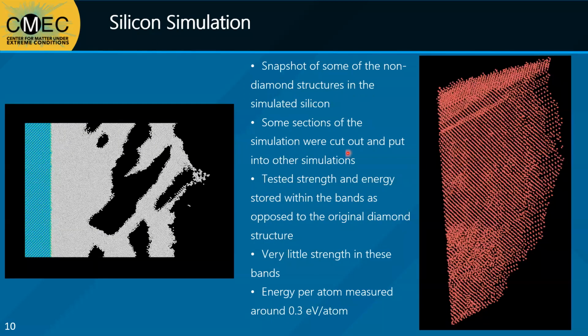On the left here, we can see a close-up of the non-diamond atoms within the system. One of those bands was cut out and imaged face-on, as seen here on the right side. When these cutout bands were tested for strength and for energy, we found that there was very little strength in these bands, and that the difference in energy per atom between the diamond phase and this phase was about 0.3 electron volts per atom. On the right-hand image, you can see that there is also a lot of long-range order that is still present within the system, although there are small pockets that may contain an amorphous phase. The goal of my research here was to easily identify the phase of these unidentified bands.